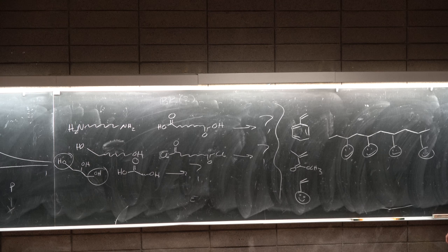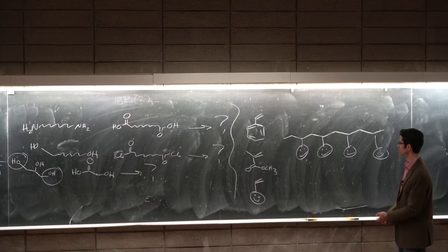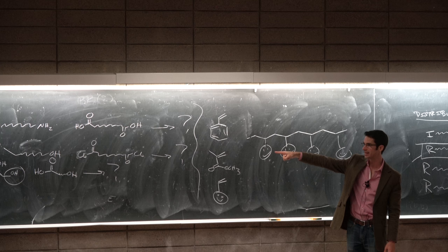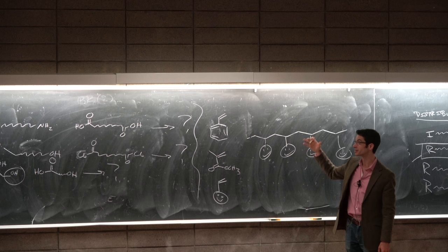And they could either be made by a free radical polymerization or a controlled radical polymerization. The free radical, just dump in the AIBN or the BPO, and it's off to the races. That's the popcorn mechanism, the uncontrolled free radical mechanism. Or it could be nitroxide mediated, ATRP, or RAFT. And the difference is that in ATRP and RAFT, you have control over what the end groups are, which is useful, and much lower dispersity of the molecular weight, and you have a linear dependence of the average molecular weight on the extent of reaction.